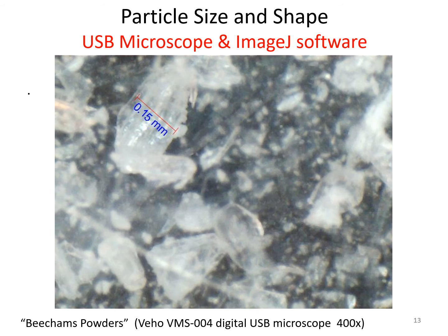One set of properties we're clearly going to be interested in is the size and shape. You don't particularly need expensive sizing and shaping equipment to do this. You can do this with a microscope and using your own eyes. This is an example of one which was taken using a USB microscope, whereby an image is taken and then in this case it's just using the microscope software to give you an idea of some of the sizes in that, although you can also use something called ImageJ software as well, which will help you identify it. So from this sort of analysis, you can see what the size is and what the shape is quite readily.